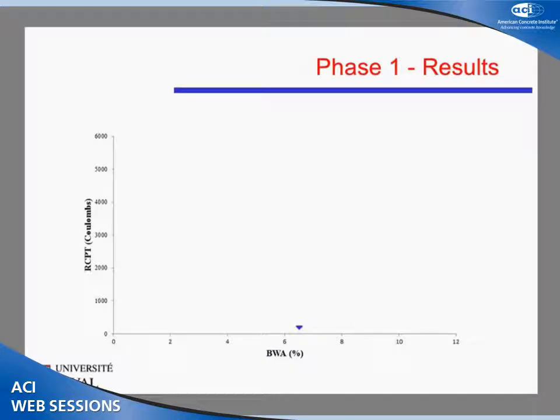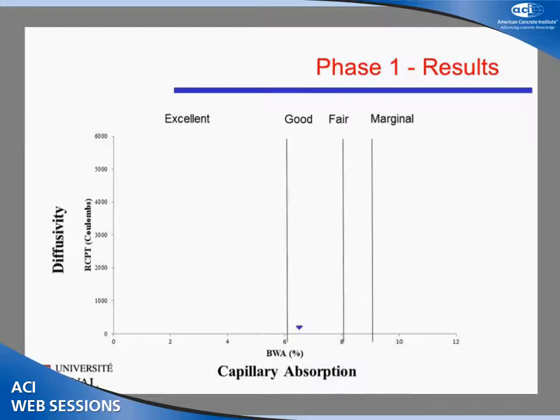So to assess the correlation between these two test results, data were plotted on a graph, what we see here, which is the RCPT results against the boiled water absorption results. It's important to know that RCPT is a test to estimate the ionic diffusion of the material. And I say estimate, it's not necessarily dead on. And the boiled water absorption test is a test that measures the capillary absorption. What we see here are the limits that were set by Mr. Morgan in this table that was discussed earlier. And these are the results from the Shotcrete mixtures that were characterized in our lab in Laval.